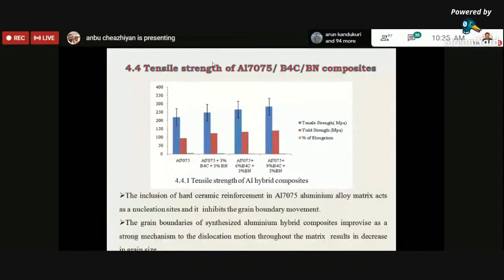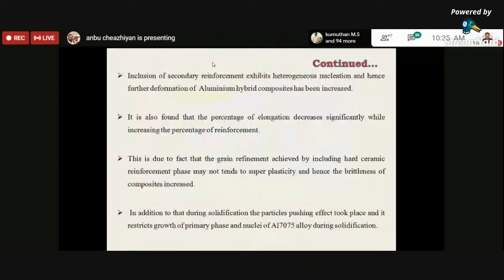So the percentage of elongation is decreased due to the increase in percentage of reinforcements, and due to the grain refinement achieved by hard ceramic reinforcement. These tend to reduce the superplasticity effect, and hence the brittleness of the composite has been increased. So this is considered to be a major reason for the reduction in percentage of elongation, along with the inclusion of secondary reinforcements.